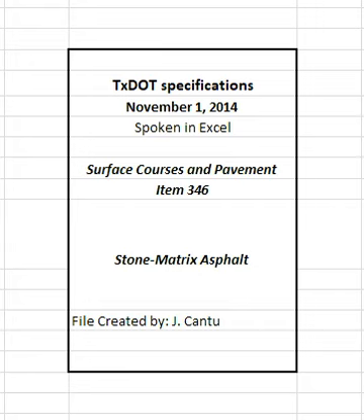2.2 Mineral filler. Mineral filler consists of finely divided mineral matter such as agricultural lime, crusher fines, hydrated lime, or fly ash. Mineral filler is allowed unless otherwise shown on the plans. Use no more than 2% hydrated lime unless otherwise shown on the plans. Use no more than 5% fly ash unless otherwise shown on the plans. Test all mineral fillers except hydrated lime and fly ash in accordance with TEX 107E to ensure specification compliance. The plans may require or disallow specific mineral fillers.